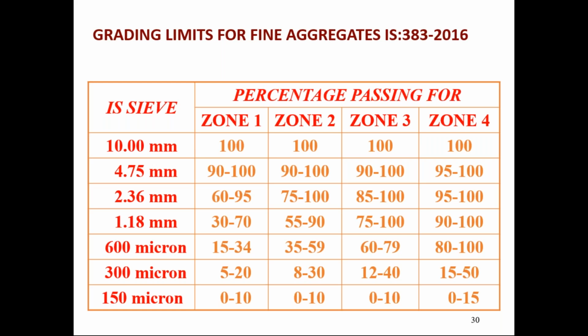Whatever the sample is, we need to calculate the percentage passing, and then compare those results with this table. If you closely observe this table, for any sand, the value at 600 micron decides which zone the fine aggregate belongs to. So 600 micron is a very critical parameter.